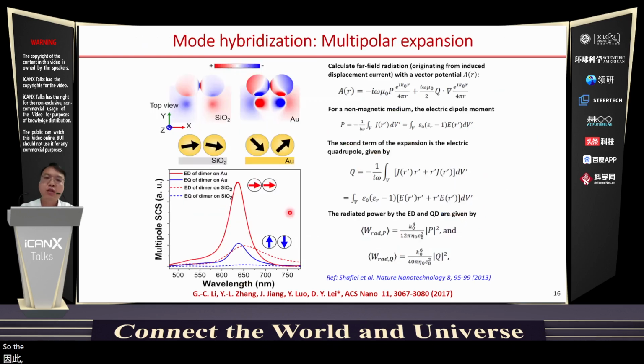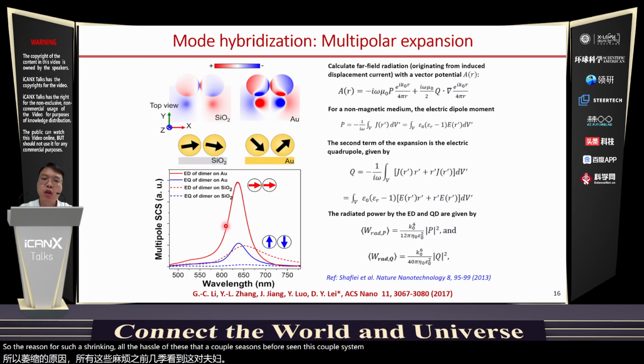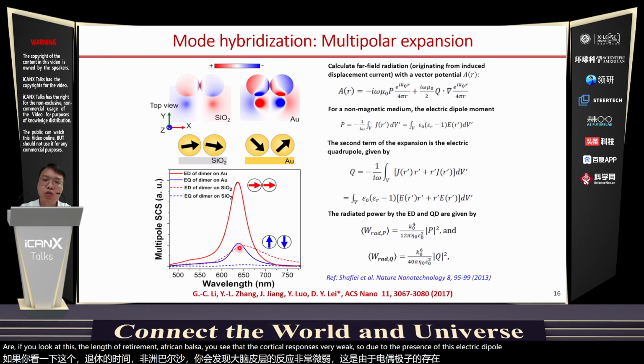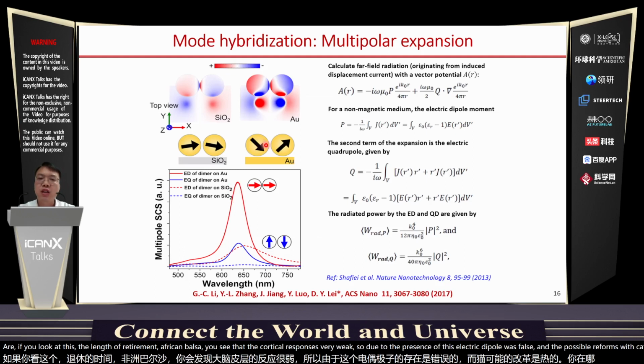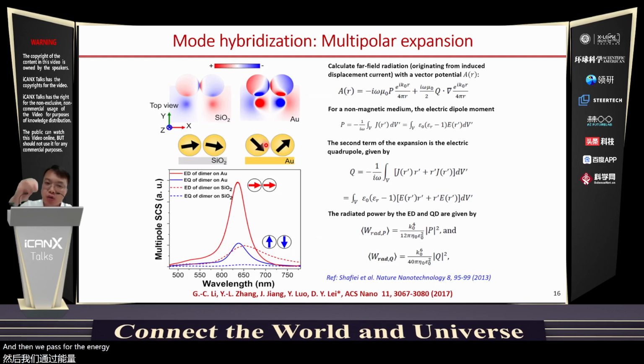The reason for such shrinking, or the enhanced quality factor, of this coupled system is that in this coupled system, we can actually invoke the magnetic response or the electric quadrupole response. That's given by the blue line. If you look at the nanosphere dimer on silicon dioxide, you see that the quadrupole response is very weak. So due to the presence of the electric dipole response and the quadrupole response, we get very efficient hybridization, and then we can store the energy in the system to get a much larger quality factor.